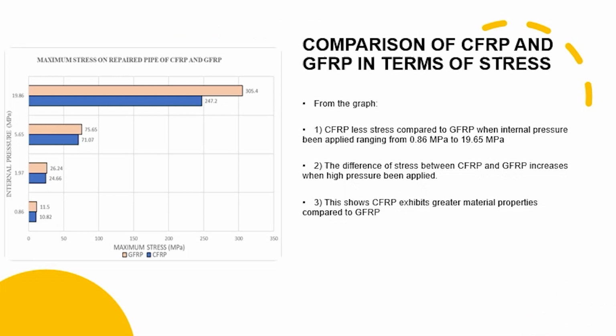This is the comparison of carbon fiber and glass fiber. Carbon fiber shows less stress compared to glass fiber when internal pressure is applied, ranging from 0.86 to 19.65 megapascal. This shows that carbon fiber exhibits greater material properties compared to glass fiber.